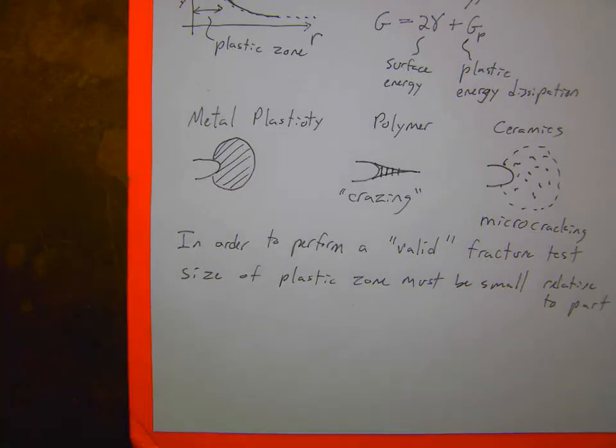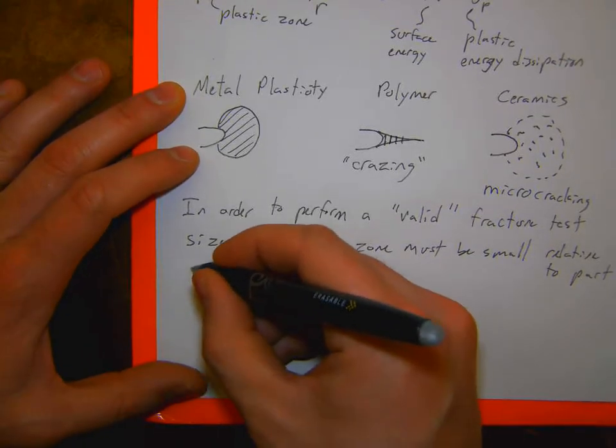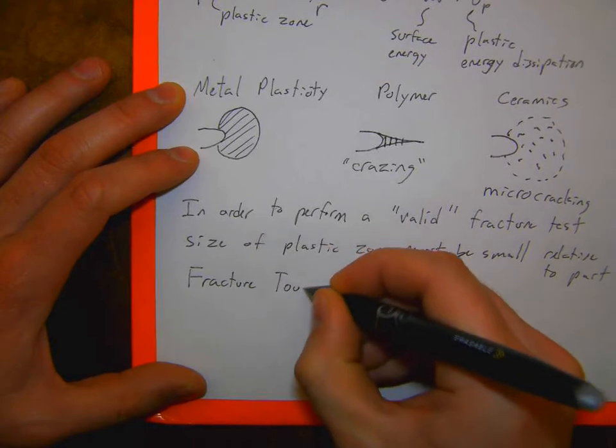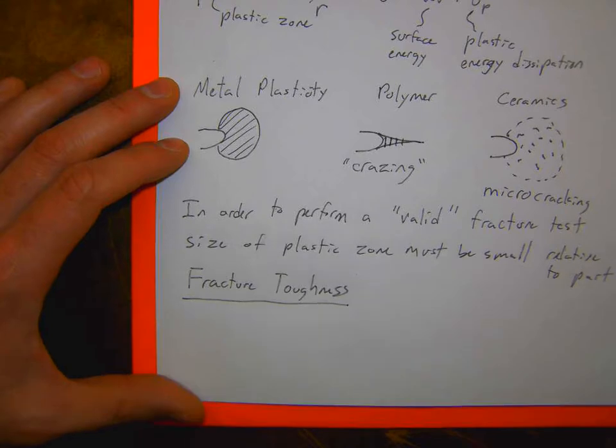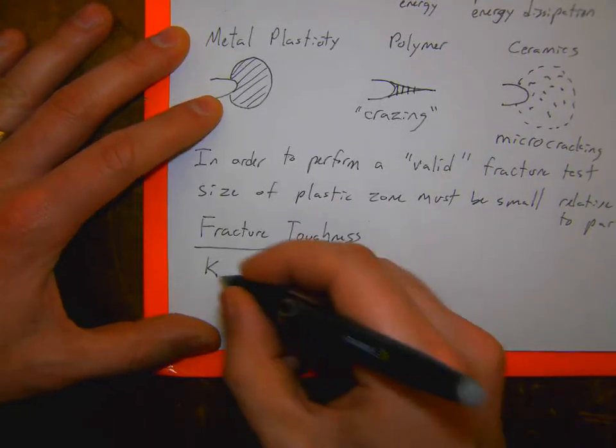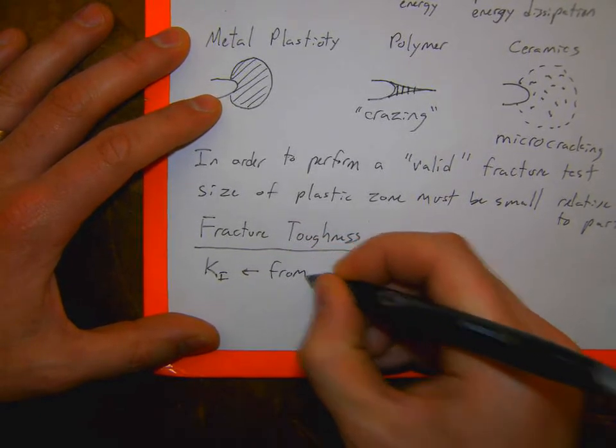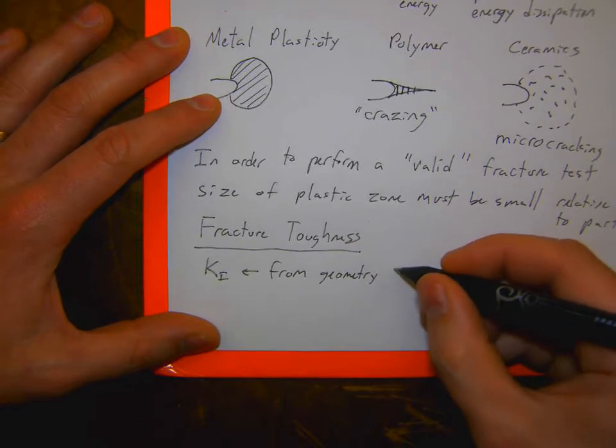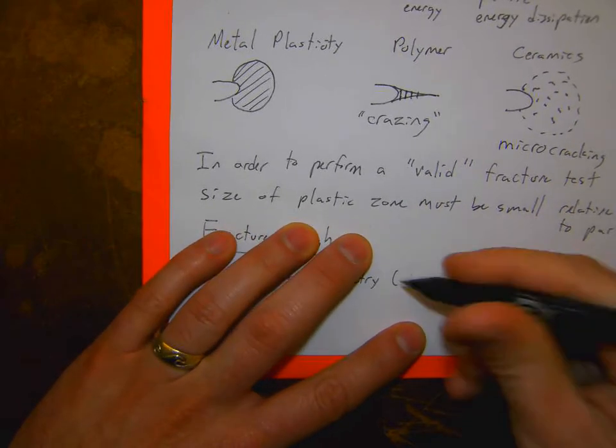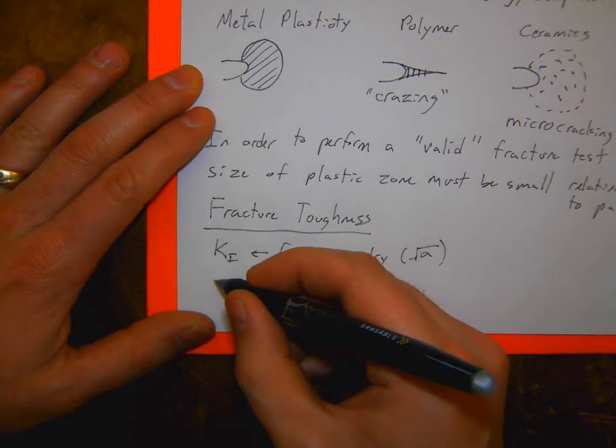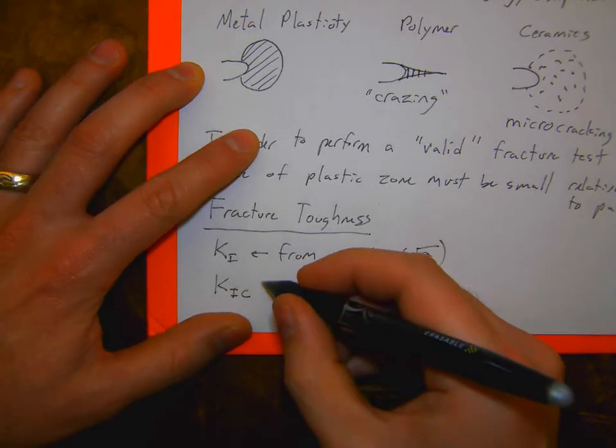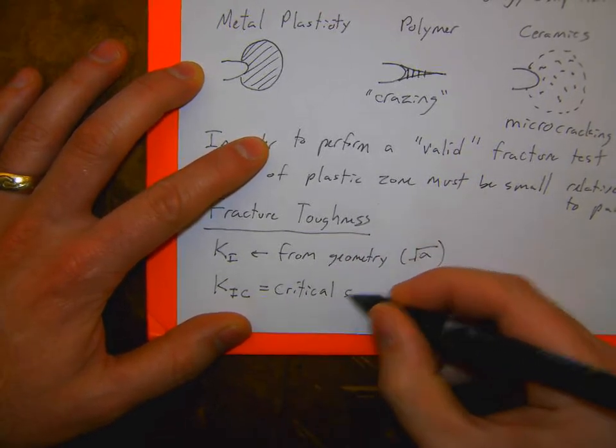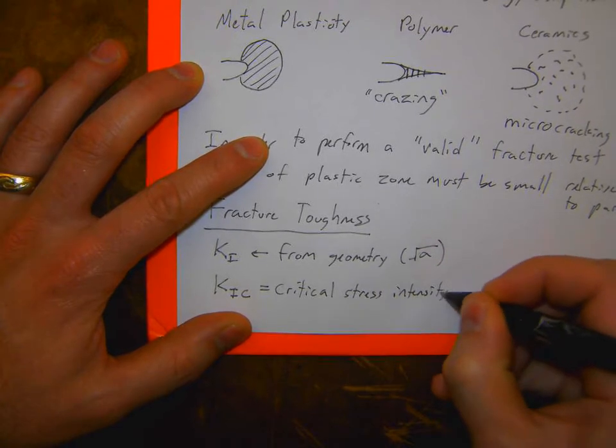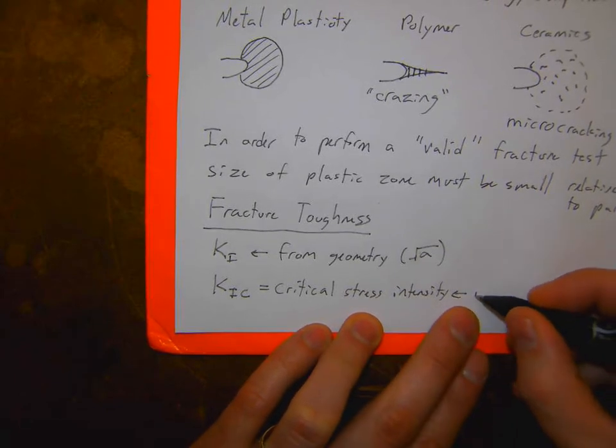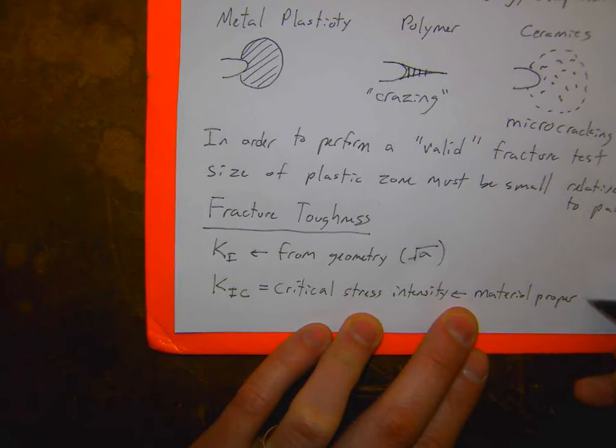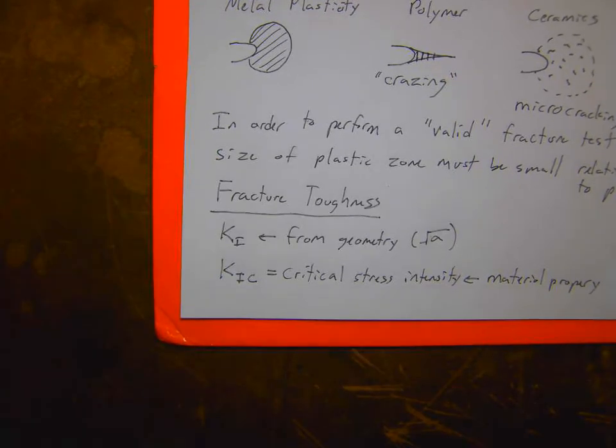Now, when we get a fracture toughness for a material, we obtain this from experiments, and we say there's some stress intensity factor, KI, which comes from the geometry and is proportional to the square root of a, the length of the crack. Then there's some critical stress intensity, KIC, which is what we're going to call a material property. So for failure to occur,